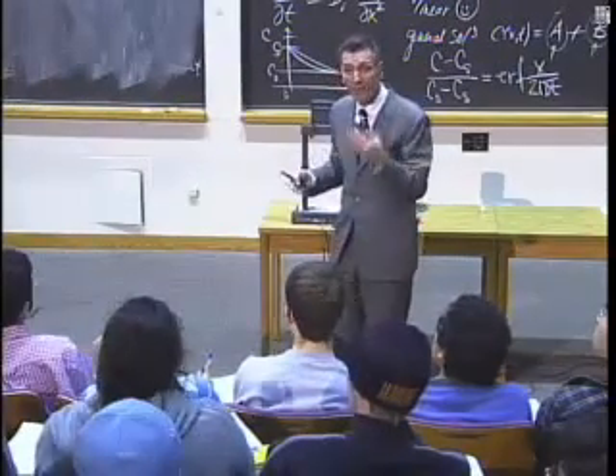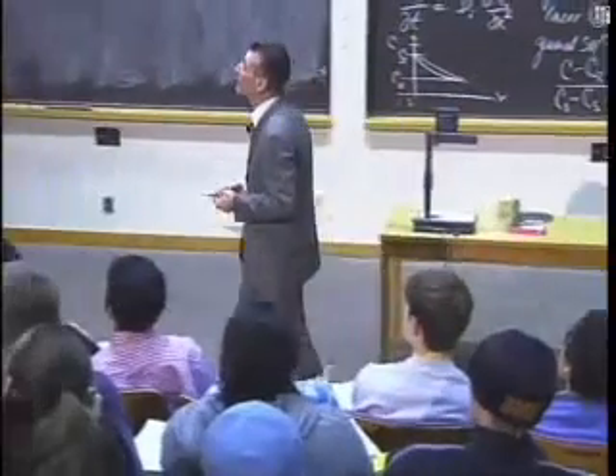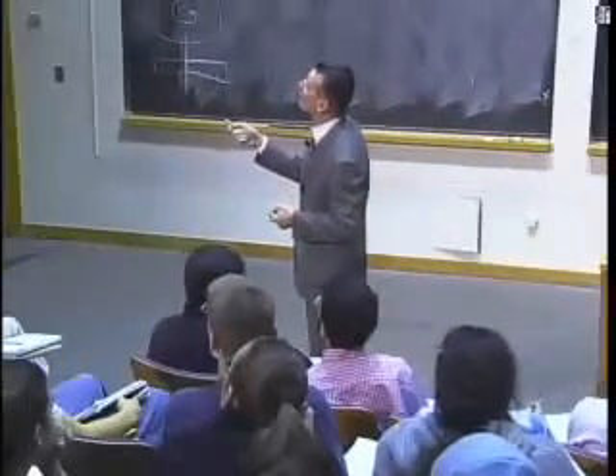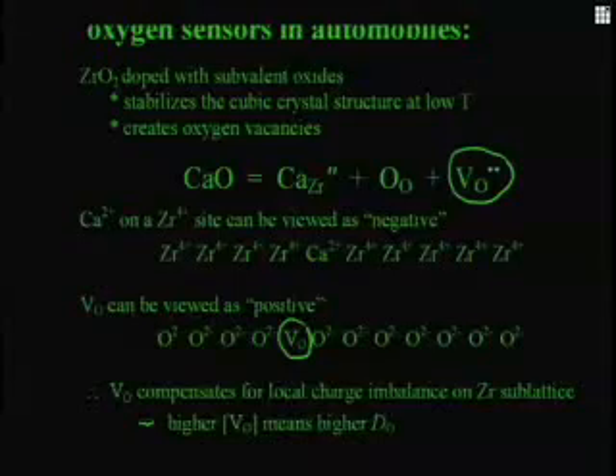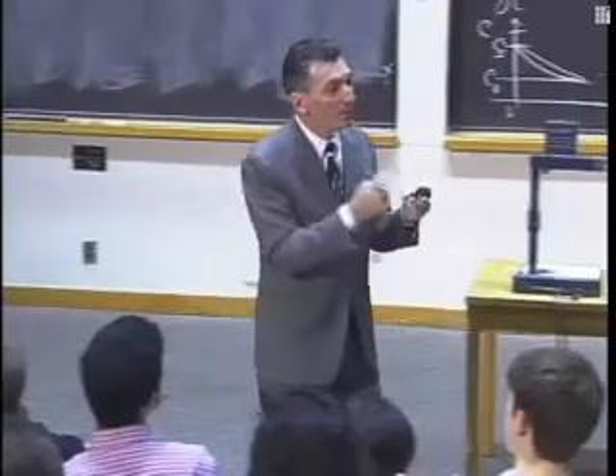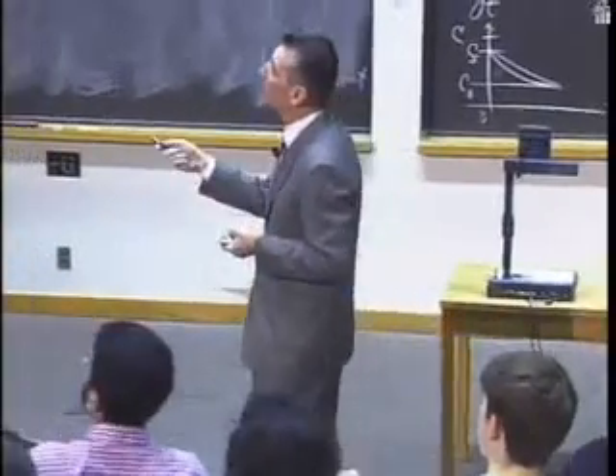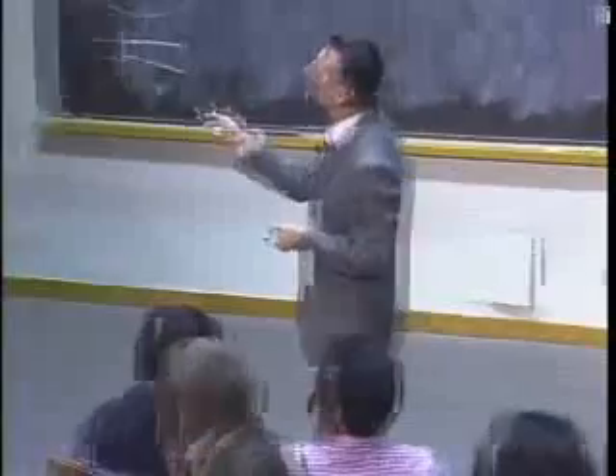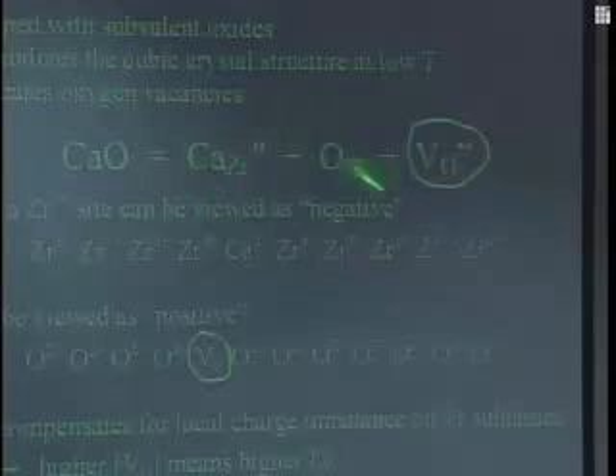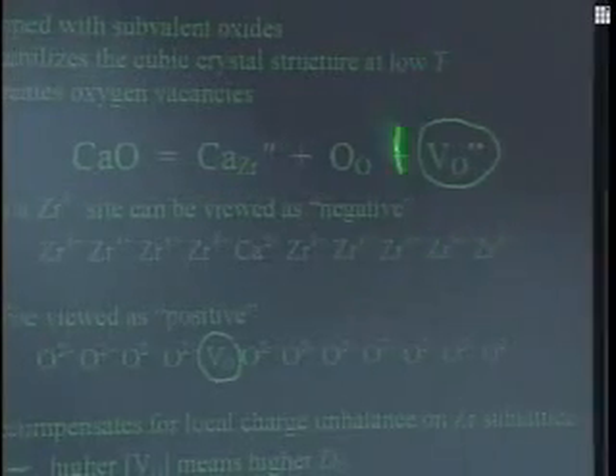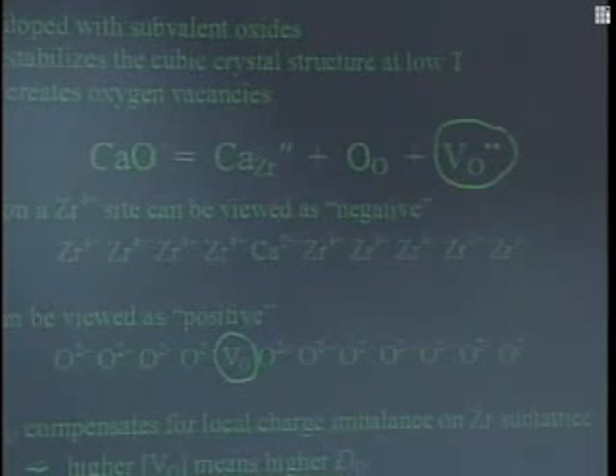So now you need to have a sensor. And that sensor looks like this. It is zirconia. It's an ionic oxide, and it's doped with calcium oxide to create oxygen vacancies. So we're going to get defects involved, and we're going to talk about diffusion. When we put calcium oxide into zirconia, we have 2+ sitting on a 4+ site, and so we need to make an oxygen vacancy to compensate.